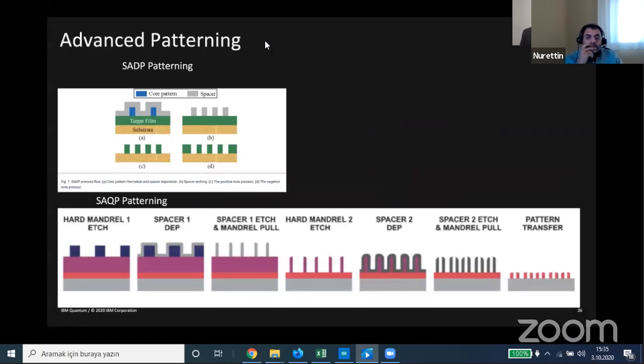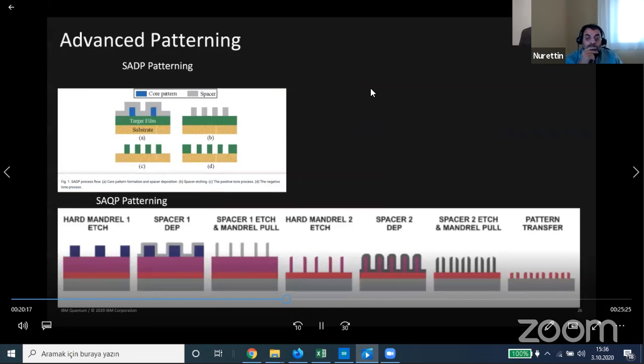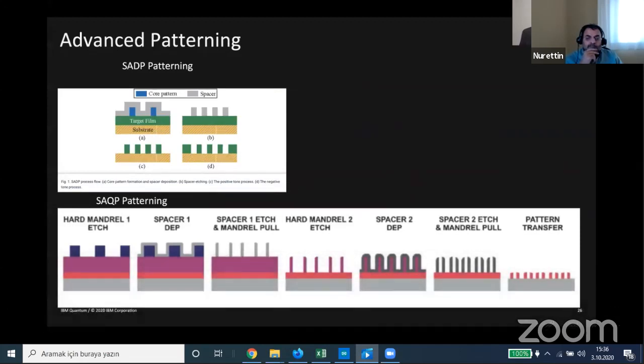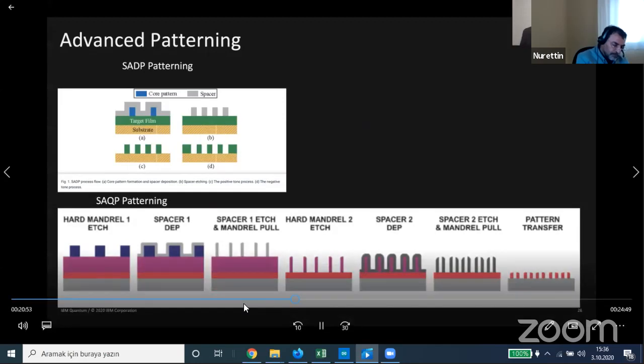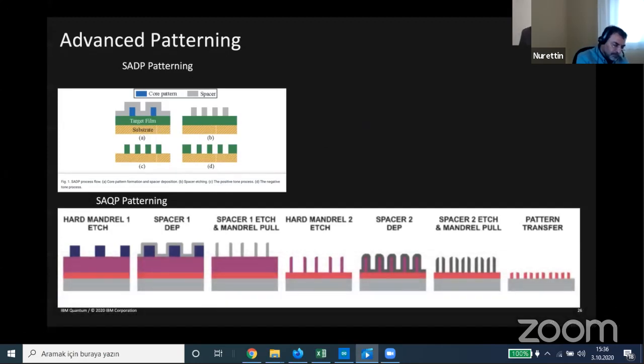So there are two techniques. One is SADP, self-aligned double patterning. So here, the concept is you start with your core patterning using UV. You form a spacer which is etched. We pull out this core pattern. We then use the spacer to etch the critical layer. And so essentially what we've done is doubled the pitch, doubled the density of those layers simply by doing it in this way. Another approach is then to build on this and do it twice. So that's called self-aligned quadruple patterning. So here we essentially do that process twice and achieve 4x the amount of density for those critical layers.